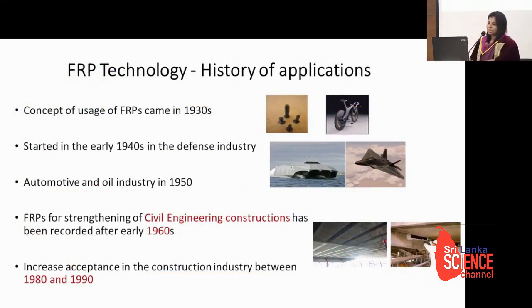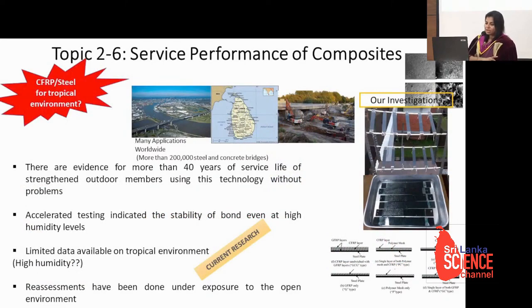Then, if you look at our service performance investigations, we see there are many steel bridges even in our country, and some are corroded, and renovation is well needed. There are applications worldwide, but limited applications in the tropical environment. So we thought to see the bond performance under tropical environment, and we tested a series of samples under a controlled accelerated environment as well as open tropical exposure, and also some bonding arrangements. In this case, we used non-corroded steel as well as corroded steel, which covers four types of corrosion. If this is successful, it's very good for our bridges.